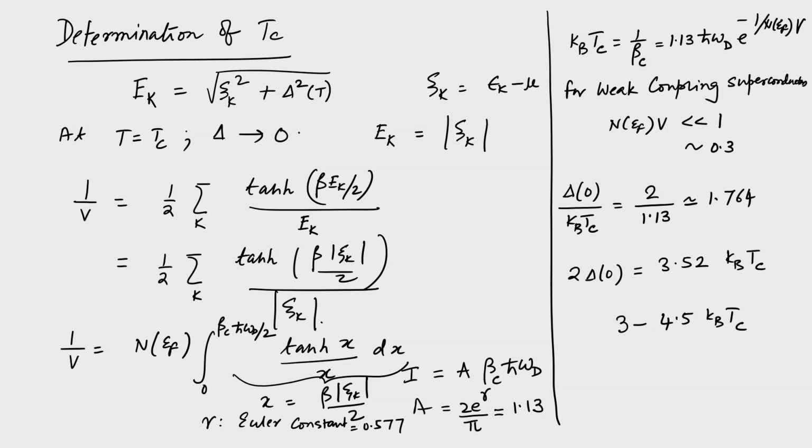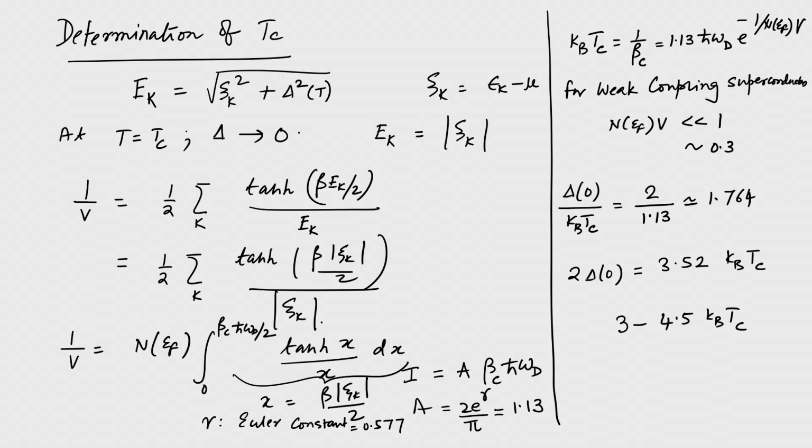So, the transition temperature of a conventional BCS superconductor is twice the gap divided by 3.52, and then the scale is kB, which is the Boltzmann constant. So, this is for most conventional superconductors. All right. So, this is what one really needs for knowing the Tc, because that is a very important quantity in the context of superconductivity.